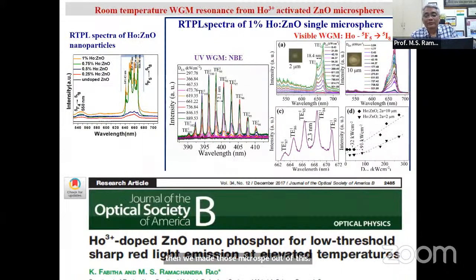This was a very interesting paper that we published. While we saw whispering gallery modes in pure, undoped zinc oxide in the UV region, by doping holmium, you start seeing whispering gallery modes in the otherwise flat intensity response in the visible light region. This is exciting - it's the first time whispering gallery modes could be seen in the visible region in doped zinc oxide.